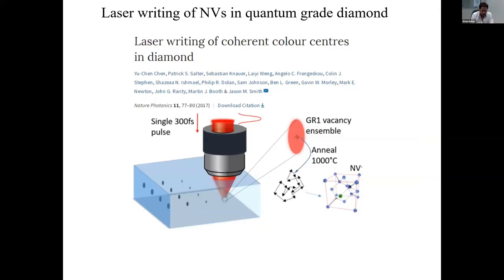Salter's group, which is a friendly collaborator of ours now, first showed that by focusing a single femtosecond laser pulse, so typically we're using many pulses to form these optical waveguides in diamond. Here they're using a single and lower energy laser pulse to very gently modify the diamond. But essentially they're producing only vacancies, hundreds of vacancies within the focal volume of the diamond. They then apply a post-thermal treatment to cause these vacancies to mobilize.